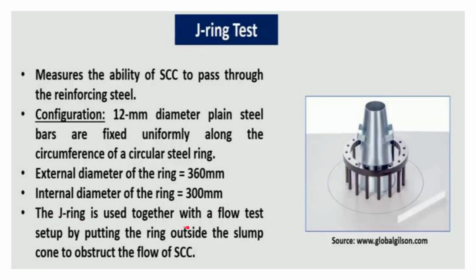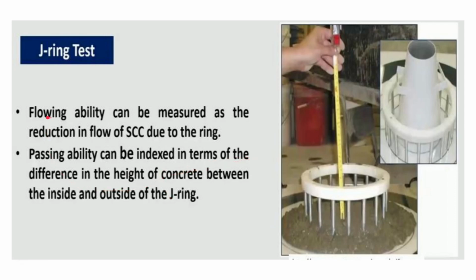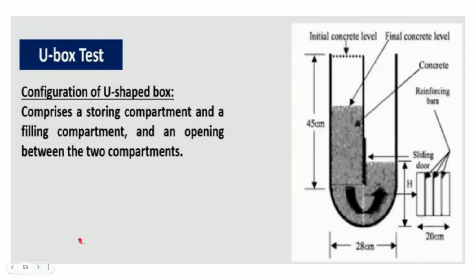The J ring is used together with a flow test setup by putting the ring outside the slump cone to obstruct the flow of SCC. So it is a combination of both filling and passing, both merged here to find the time. How it is done: flowing ability can be measured as the reduction in flow of SCC due to the ring, because the flow will definitely get reduced. Passing ability can be indexed in terms of the difference in the height of concrete between the inside and outside of the J ring. That will give the value of the passing ability. So that is the test.